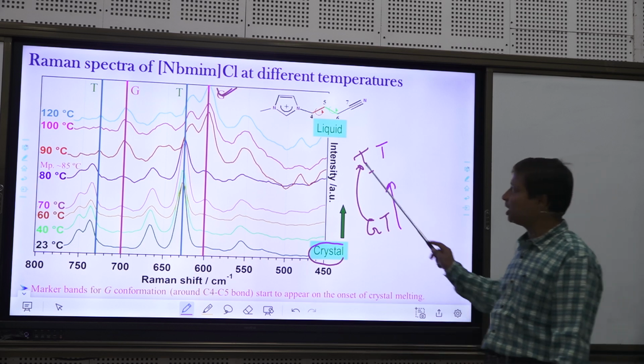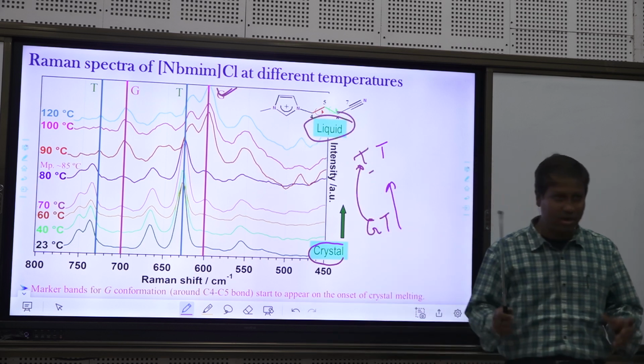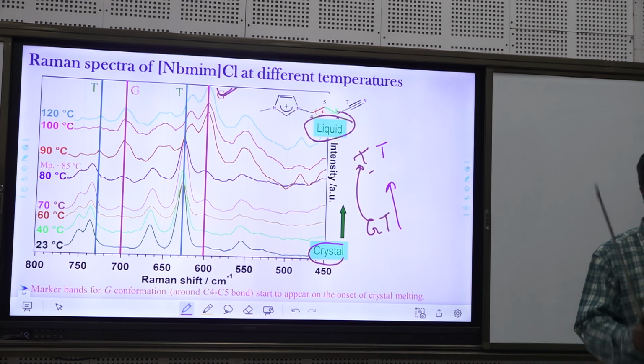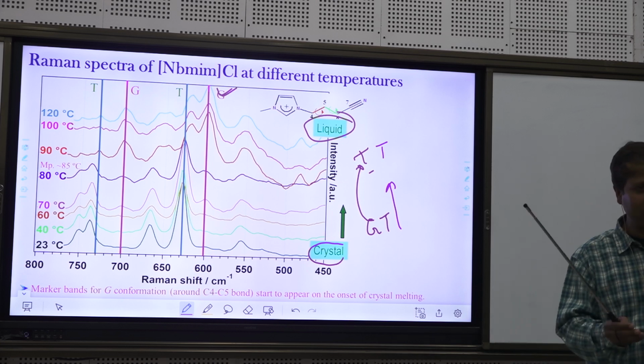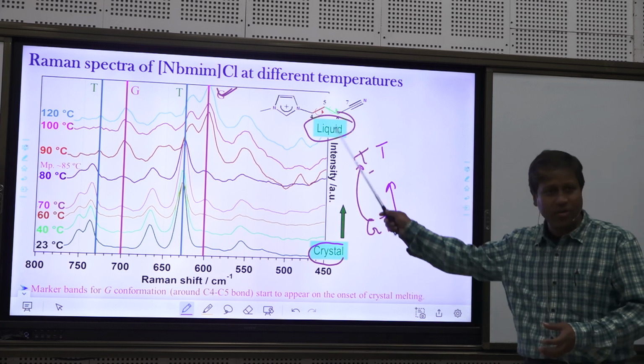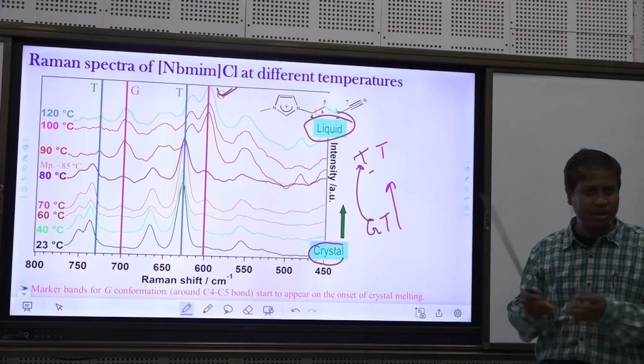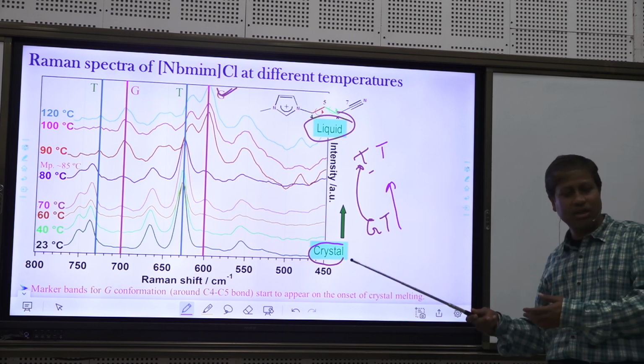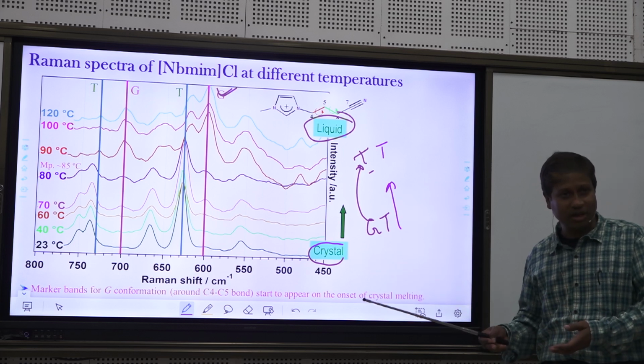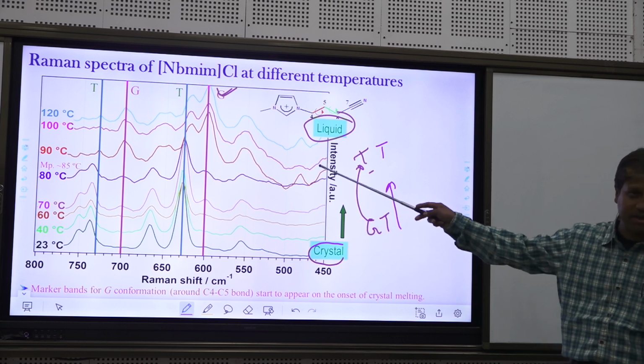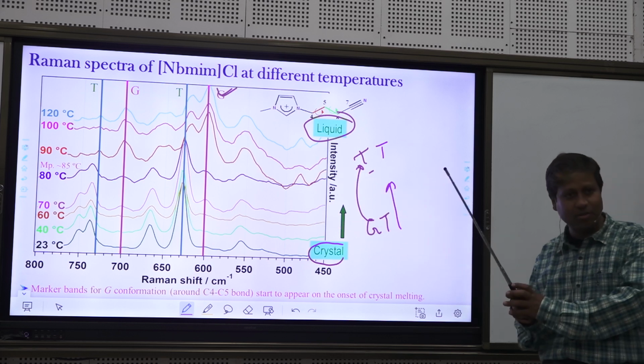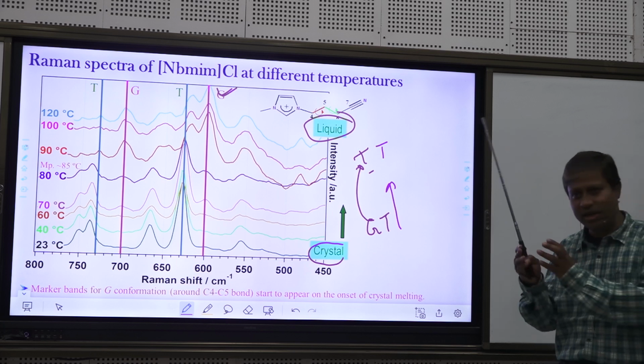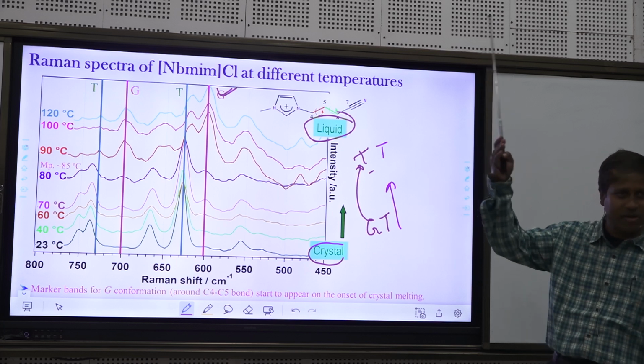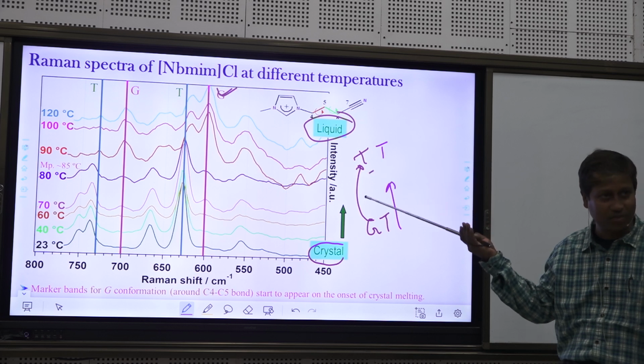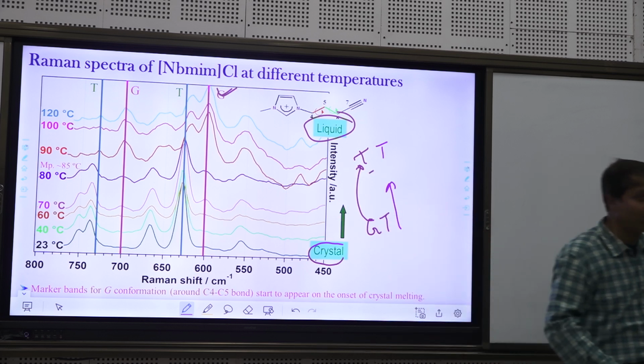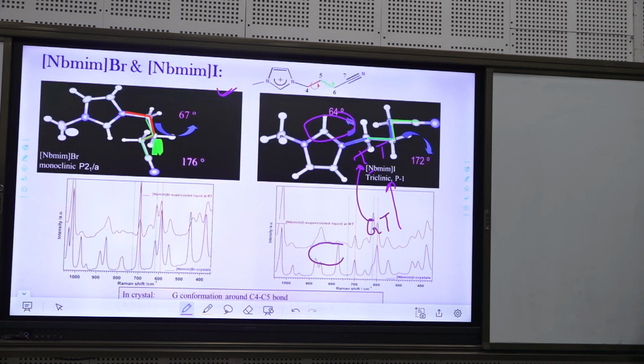So this also says that in your liquid, even if you start with a conformationally pure ionic liquid, gauche-trans, when you melt it without exposing it to air or anything, you see that you have multiple conformations. This is given by the Raman studies, because you have identified the trans marker band and the gauche marker band. Initially there is only the trans marker band; when you heat it and melt, you see the arrival of the gauche marker band. So a big conclusion can be drawn from this experiment.